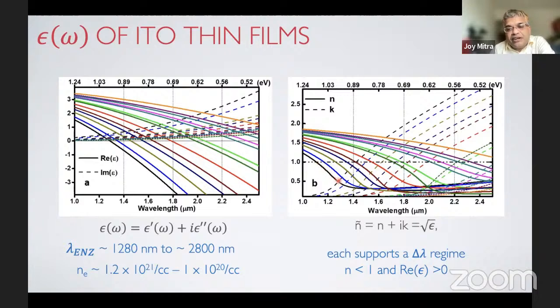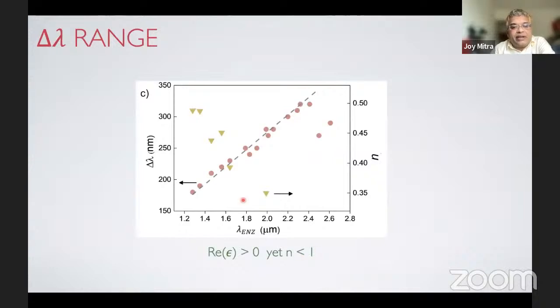But as I repeatedly said, please remember that there is this small region here, approximately 200 to 300 nanometer below the lambda ENZ, where the refractive index is below 1, as well as the relative permittivity is positive. So this is that delta lambda region, typically 200 to 300 nanometer, where we can play these tricks. And these are the refractive indices at the corresponding lambda ENZ. You can see that the refractive indices are typically around 0.4 and so on and so forth.